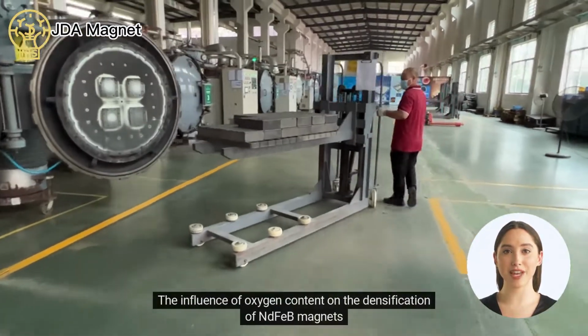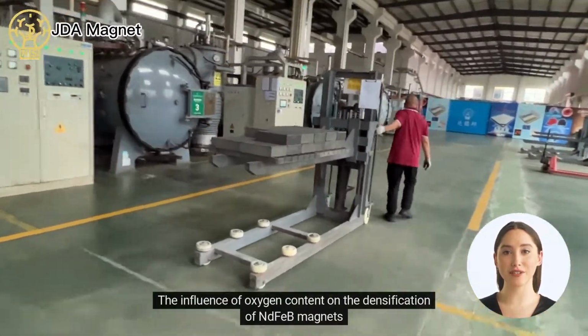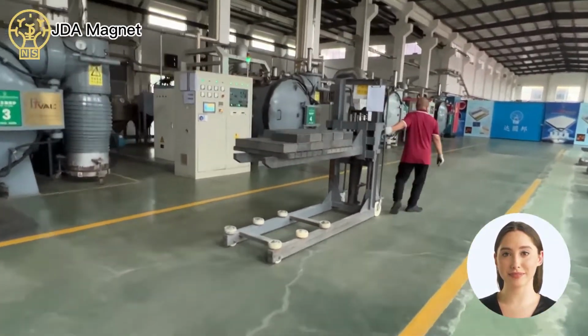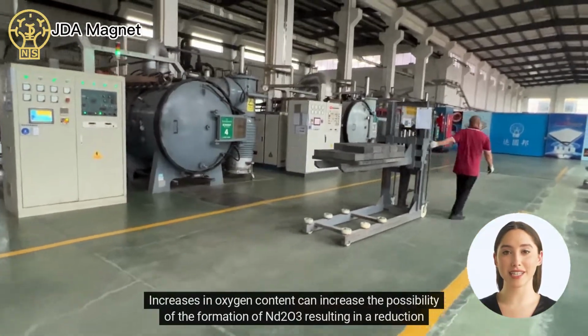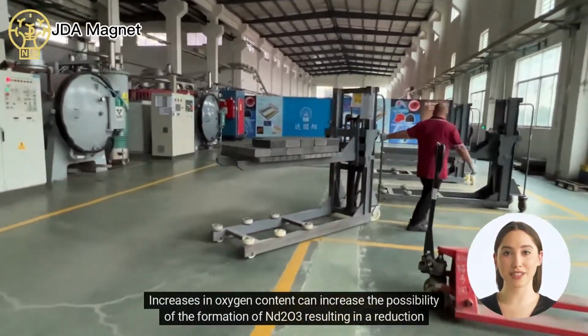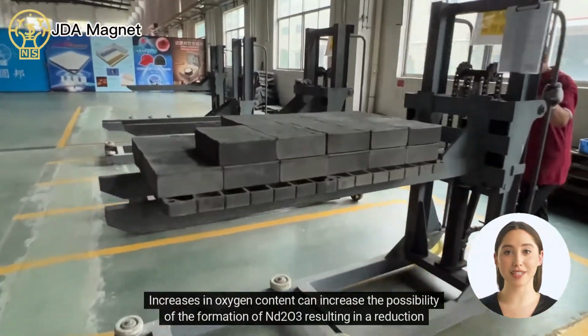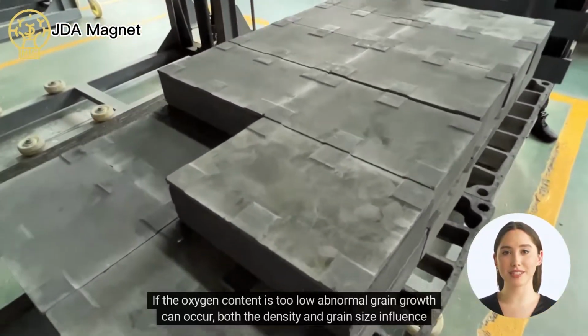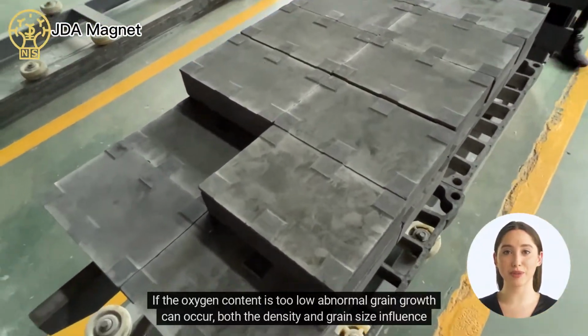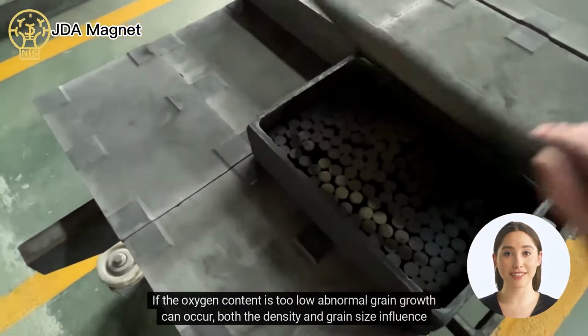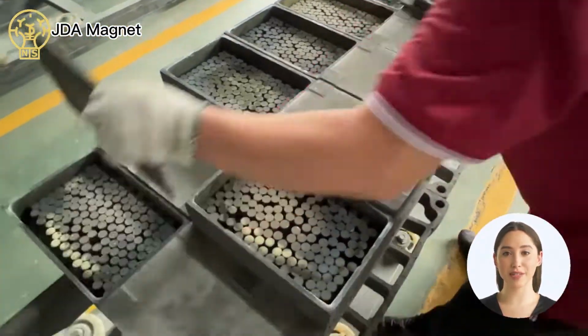The influence of oxygen content on the densification of NdFeB magnets. Increases in oxygen content can increase the possibility of the formation of Nd2O3 resulting in a reduction in density. If the oxygen content is too low, abnormal grain growth can occur. Both the density and grain size influence the magnetic properties.